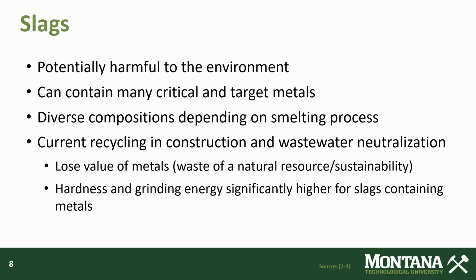And as we'll see on the next slide, slags can have a large variety of compositions depending on what process they came from and what was being smelted. So further, current recycling methods incur a loss of metals value, which is a waste of natural resources and decreases sustainability of the recycling process. Also, if the contained metals are not removed from the slags prior to recycling of slag that is currently done, the grinding energy is greatly increased and the slag hardness is much higher.